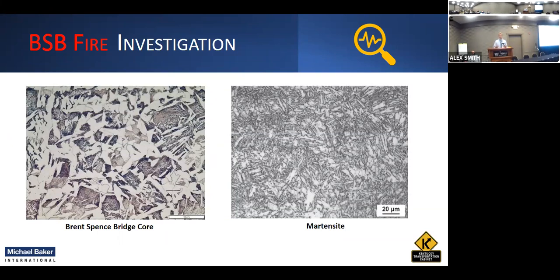We could then go back through and report up the chain that whatever that little notch or indication was, was an anomaly. They went and cleaned it up. We do not have a concern that they have changed the properties of the structure, and they could reopen it to river traffic. Again, there's as much commerce running underneath this bridge as there is running over top of the bridge, which is a major concern for all those parties involved.